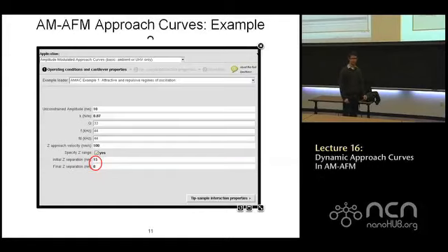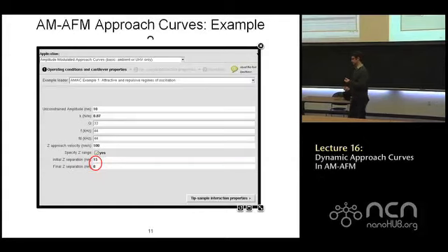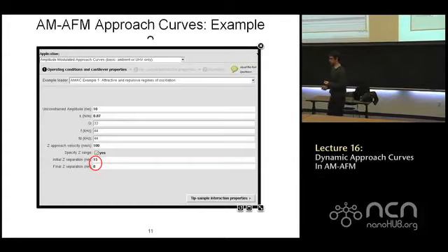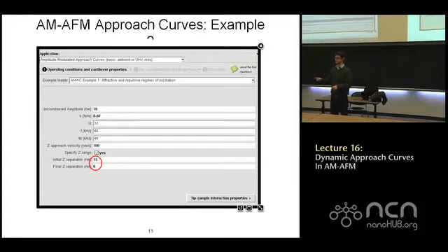One thing I've noticed is that if you eliminate the Z piezo from the plots you're looking at, if you plot phase versus amplitude ratio, it suddenly becomes much more reproducible. For instance, if we were trying to match experimental data to the simulation. That's because I don't really trust the Z piezo measurement so much when we're sweeping over large ranges.